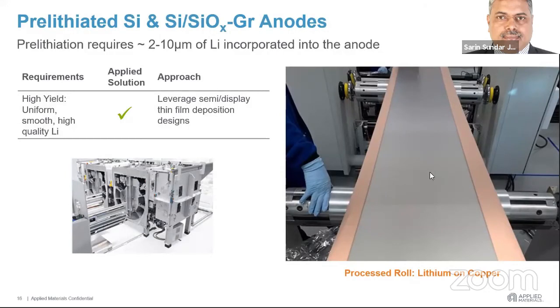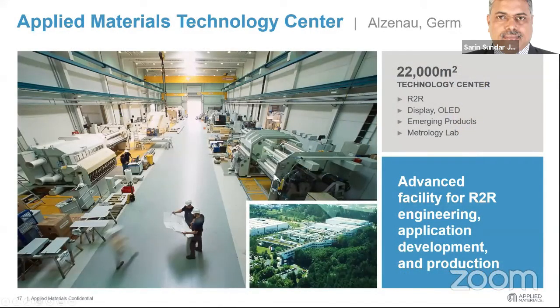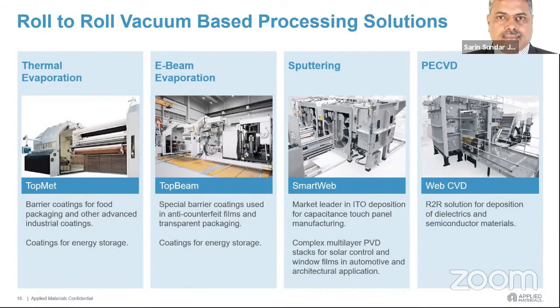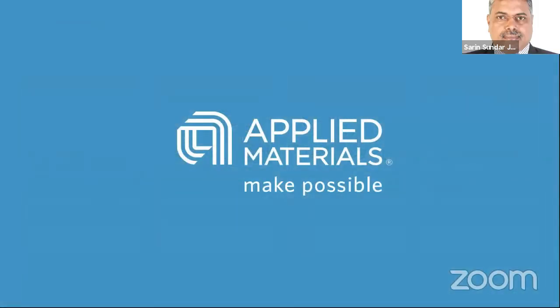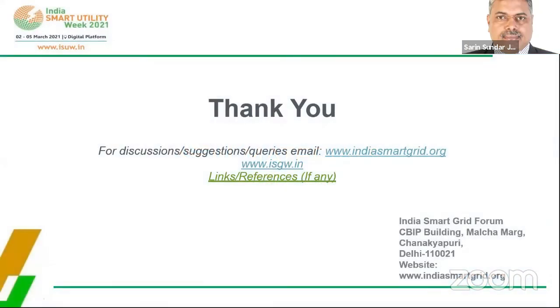And here in this picture, we show our equipment, where on the right I can see lithium metal deposited on 800 millimeter wide, 6 micron thick copper foil. And we have equipment which can roll foils up to 4.8 meters long. And typically this equipment runs at very, very high speeds. And this is from our German Technology Center from Alzenau. And we also have other equipment similarly for thin film deposition of various layers required for high volume manufacturing of lithium batteries. So that's all I have. So thank you very much.